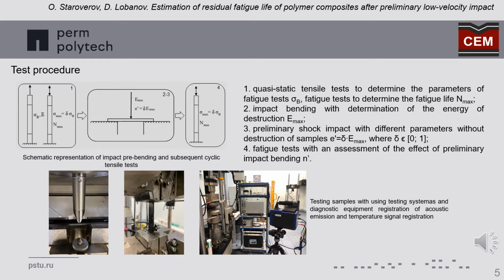The study was carried out with a preliminary shock impact by a falling weight according to the 3-point bending scheme, and subsequent cyclic stretching. In accordance with the developed technique, the value of the strength limit of the carbon fiber under study was determined from a quasi-static tensile test.